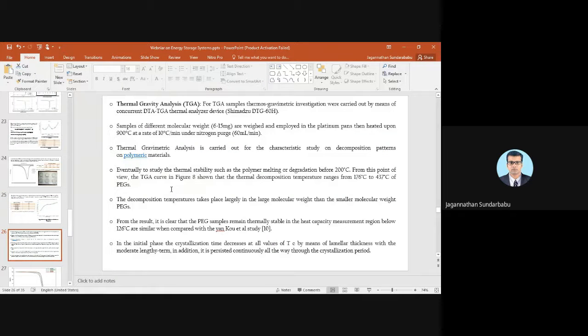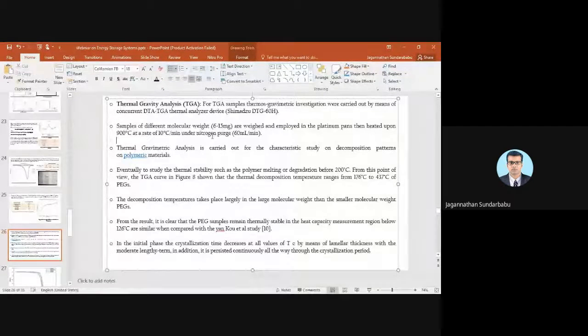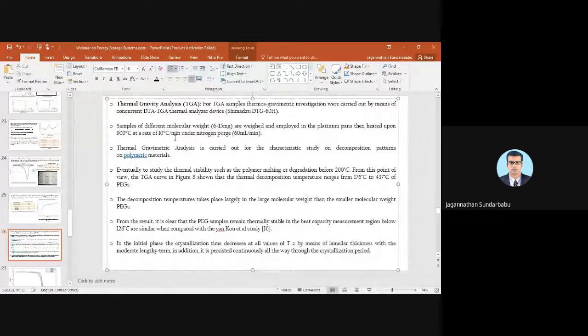And the next one is thermal gravimetric analysis, which has been carried out with samples of 6 to 15 mg weighed and placed in platinum pans, right? With heating up to about 900 degrees Celsius at 10 degrees Celsius per minute under a nitrogen purge, right? The nitrogen flow is 60 milliliters per minute. So this is the sampling process, all right?